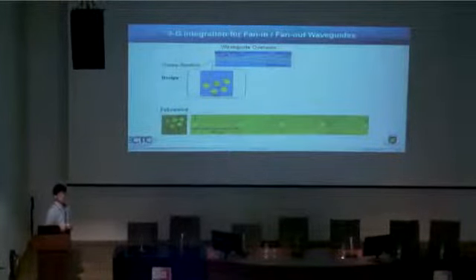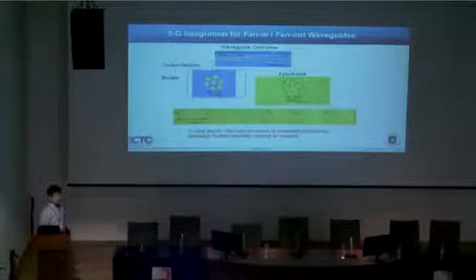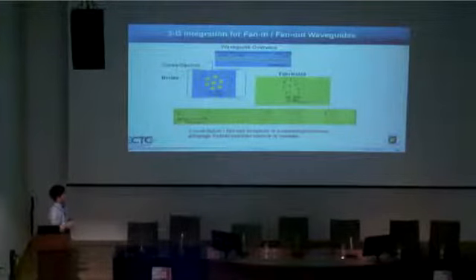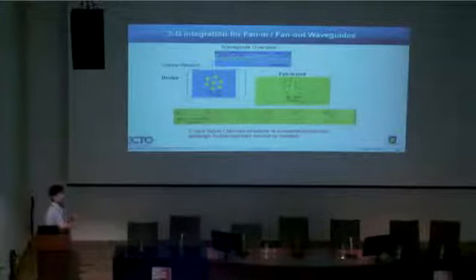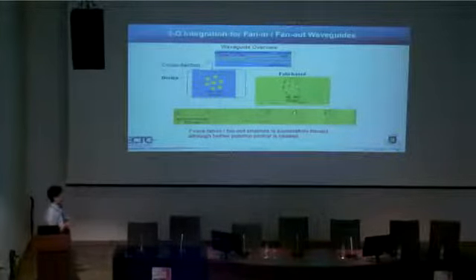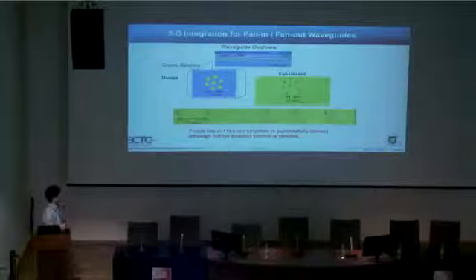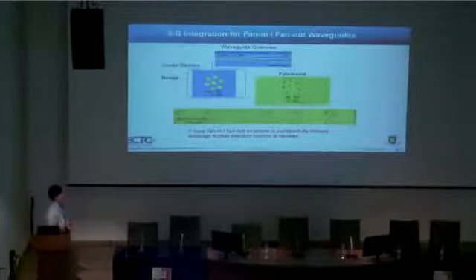And then we increased the core number to 5, and we succeeded. And finally, we tried to fabricate 7 cores for fitting to the structure of multi-core fibers like this. At one end, the hexagonal stack of the cores is formed, while at the other end, these 7 cores are widely open to 250 micron.